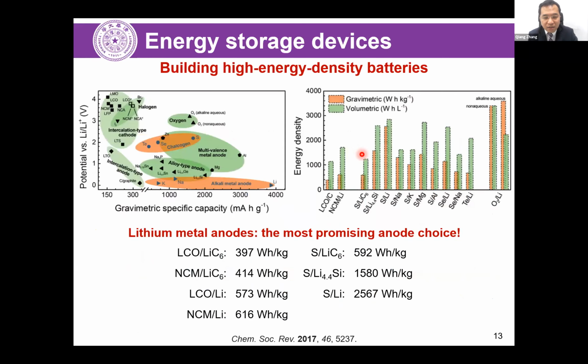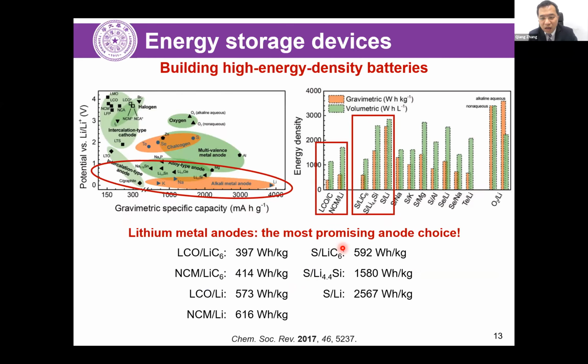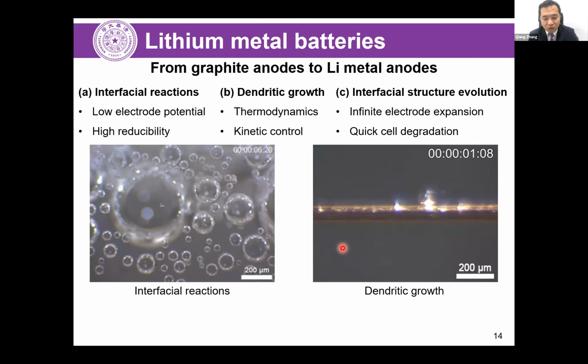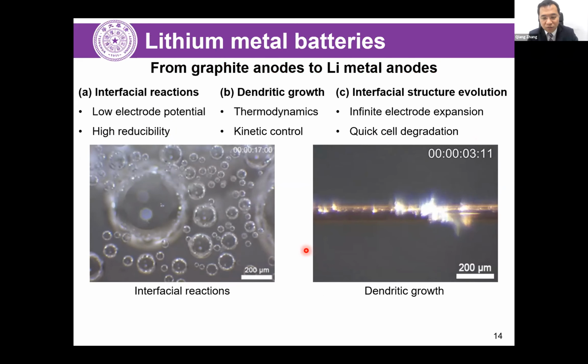The first one is how to utilize lithium metal at high utilization. In fact, if we check the cathode and anode pairs, it is found that how to reach high utilization is the first step. And the second one is that in a working battery, during repeated plating and stripping, the lithium metal anode is not always deposited in a continuous form.